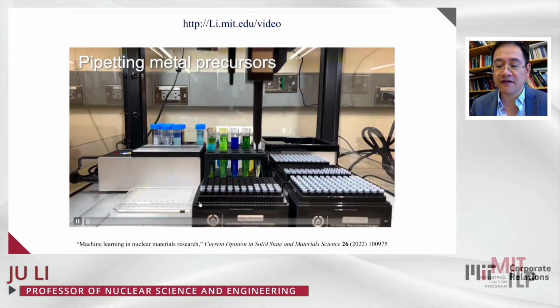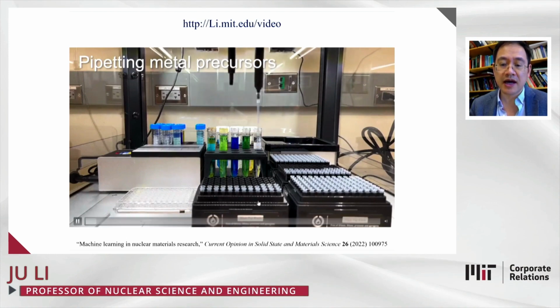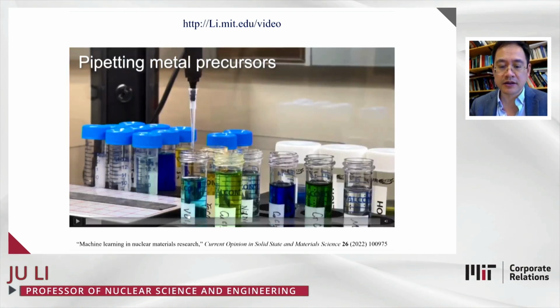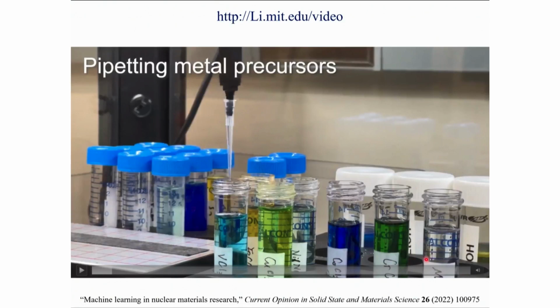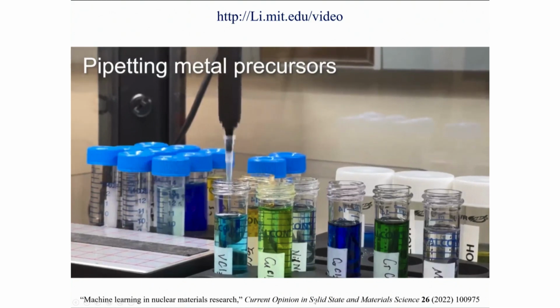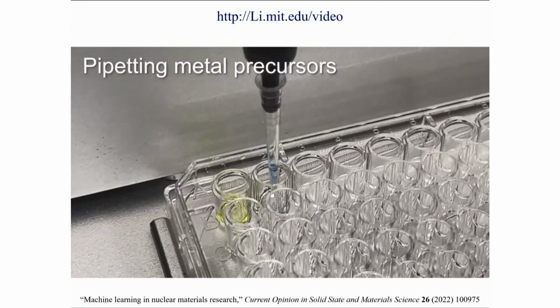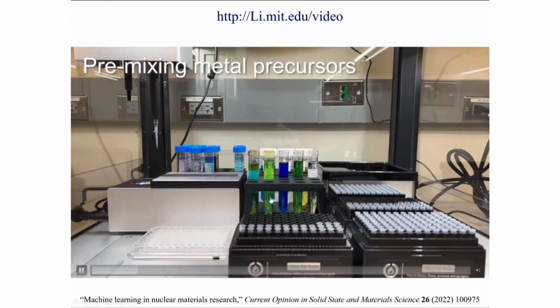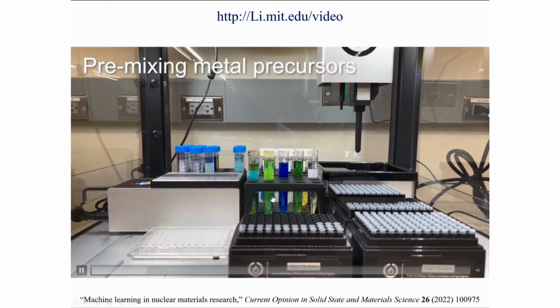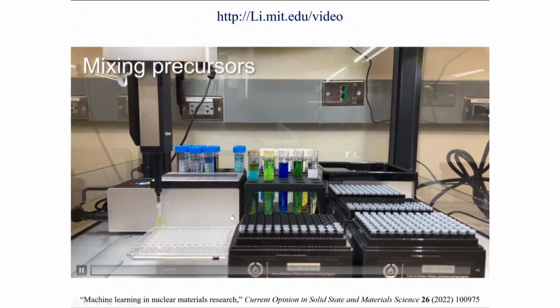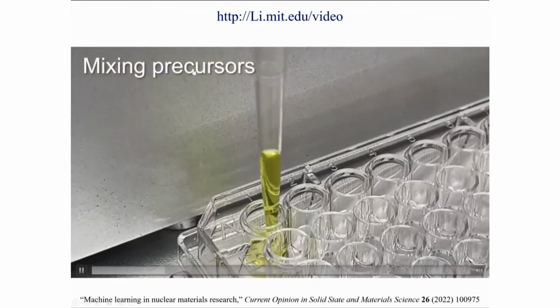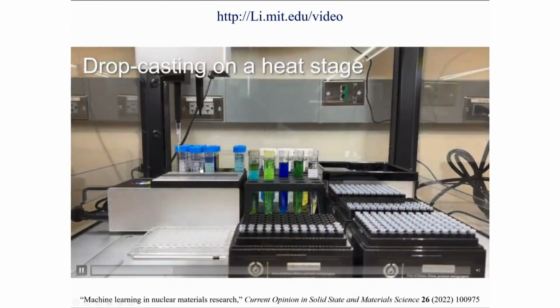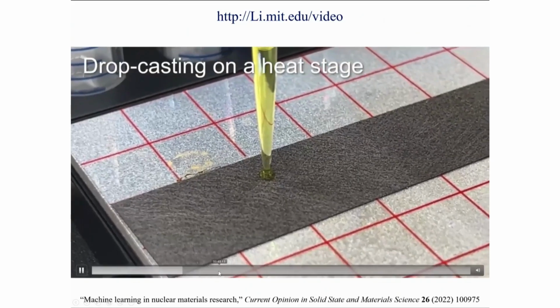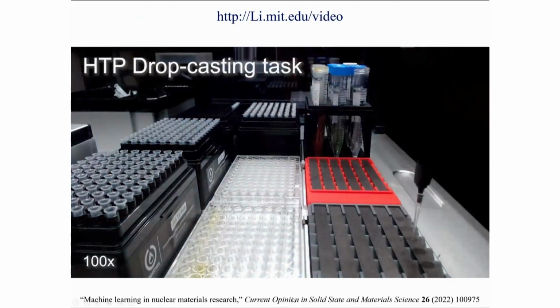And last year, we have been using this approach to design catalysts. So what you see here is vanadium, copper, nickel, cobalt, chromium, manganese. So these are precursors of transition metal salts. And we first pre-mix them in a vial here to make a multi-metallic precursor solution. And then we drop cast this multi-metallic solution onto a carbon substrate. And this shows you a fast forward view of that.